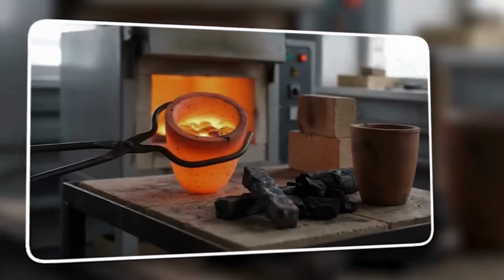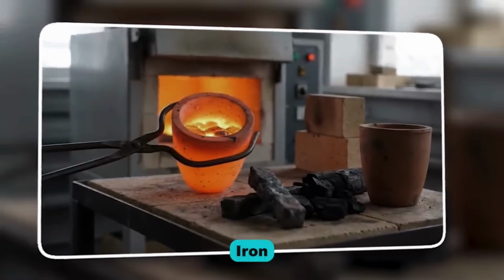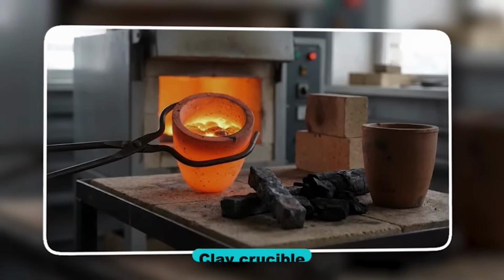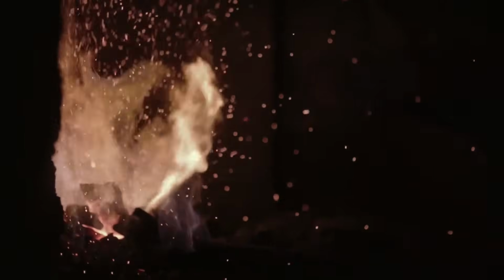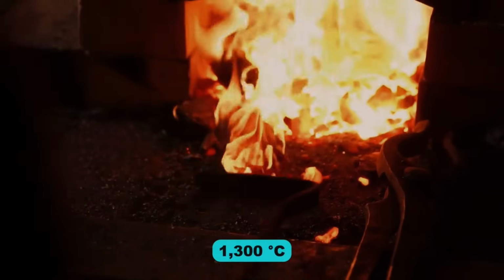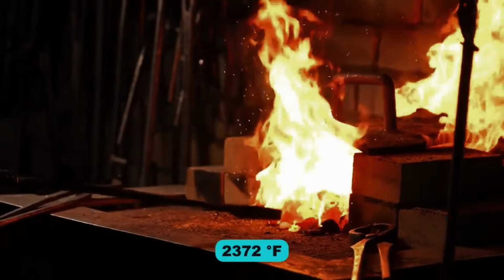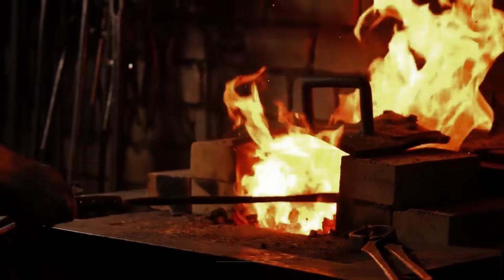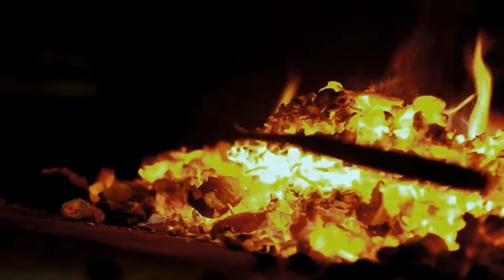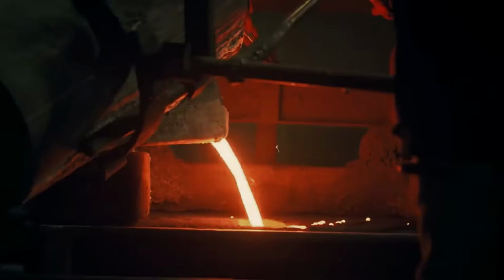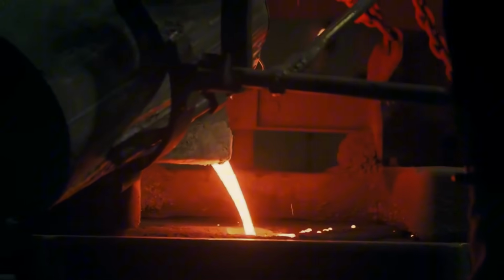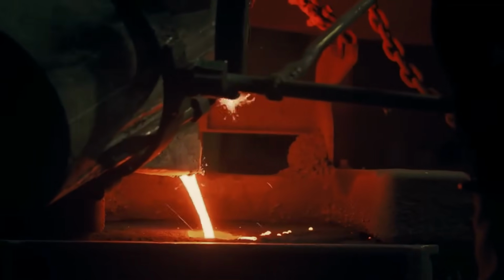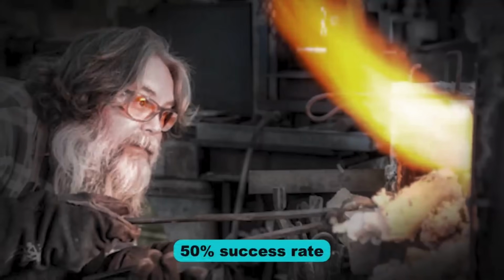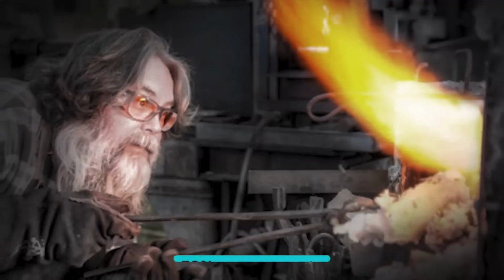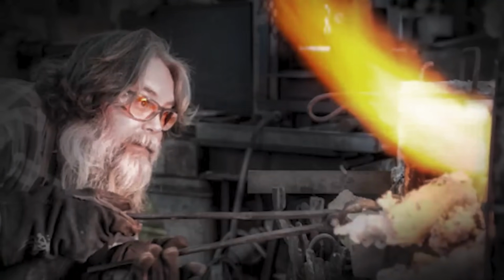In theory, the materials needed to make Wootz are simple: iron, carbon, a clay crucible, and a hot enough fire. In practice, however, the process is extraordinarily difficult because the temperature must reach above 1,300 degrees Celsius or 2,372 degrees Fahrenheit, the carbon content must land in a narrow range, the cooling must be slow and controlled, and without the right trace elements in your iron, you may produce crucible steel but never achieve the banding. Rick Furrer's 50% success rate on forging alone tells you how unforgiving the material remains even for an expert.